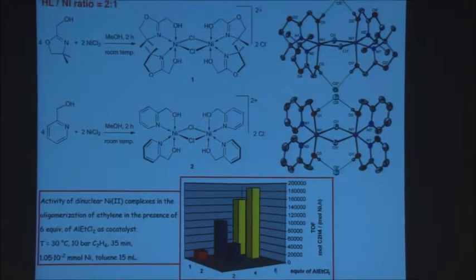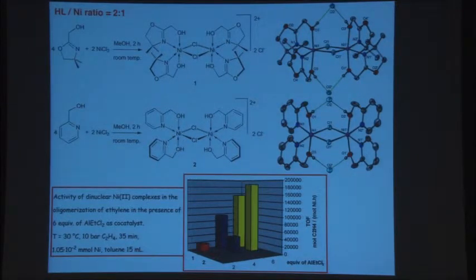So we started with very simple ligands, which is here an oxazoline type alcohol. This 5-membered ring is an oxazoline. If you react it with a ligand to metal ratio of 2:1, with nickel dichloride, methanol, room temperature, 2 hours, you form a dinuclear compound. Now you see the nickel centers here are in an octahedral coordination environment. 2 chelates per nickel, that corresponds to the stoichiometry. 2 bridging chlorides, and this is a dication, so the 2 chlorides here act as counterions.